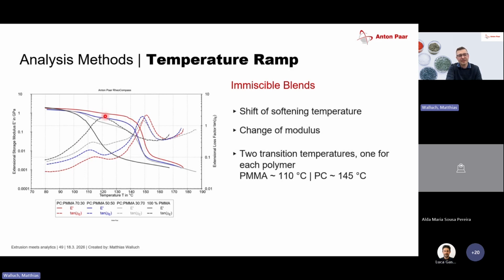And what else we can see is that we have one peak here and a second peak here. This means that the materials still are not one material. So even if we mix them and we solidify them, at the end of the day, there are still regions that are PC and regions that are PMMA. So this means that they are not miscible.